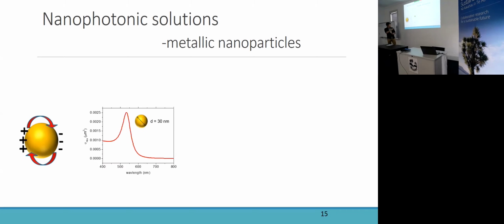So I'll start with the nanoparticles. The simplest form of nanoparticle would be a nanosphere. Here's a gold nanosphere. It has a diameter of, let's say, less than 100 nanometers. When a beam of light shines on the nanosphere, the conduction band electrons inside the nanosphere collectively oscillate with the external field, which is known as the excitation of localized surface plasmons. As a result, the incident light is localized or absorbed by this nanoparticle. Here is the absorption spectrum of the nanoparticle, and we can see that at the wavelength of 530 nanometers there's a peak, which means the green light is absorbed by these nanoparticles.